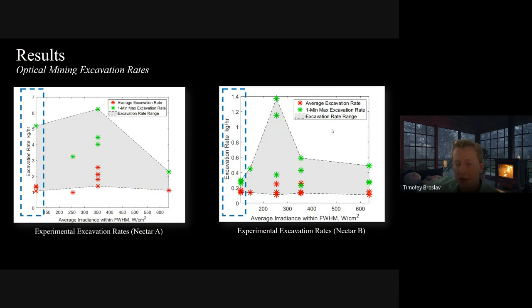But between Nectar A and Nectar B, you can notice a significant difference in excavation rate. Nectar A had approximately 4 to 5 times higher rate. Both, however, show an increase as you go up in irradiance, and then a sudden decrease as you go to higher irradiances. This is thought of as an increase in melt formation, as well as softening of the material as it gets hotter, because you have a much higher irradiance beam heating it.